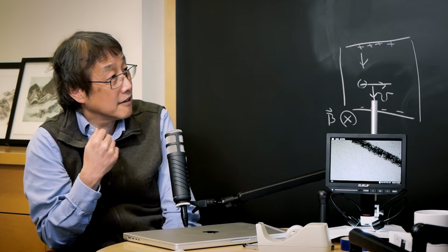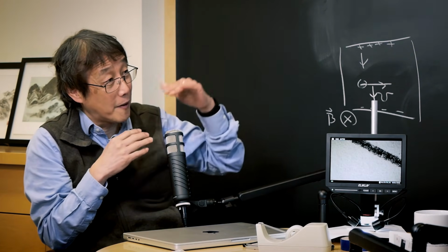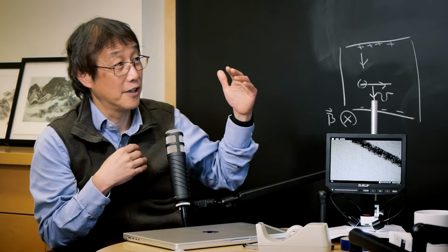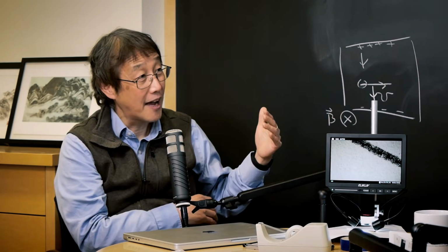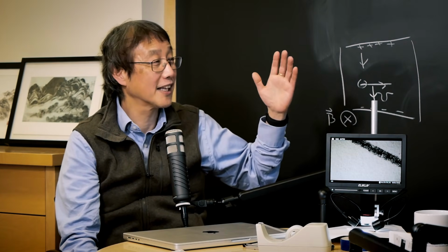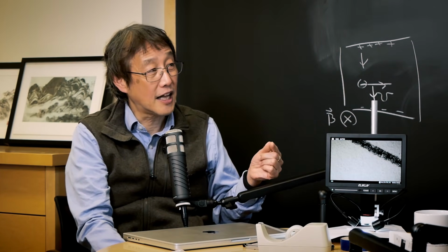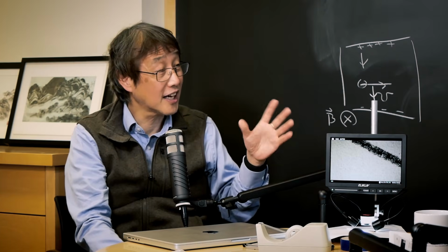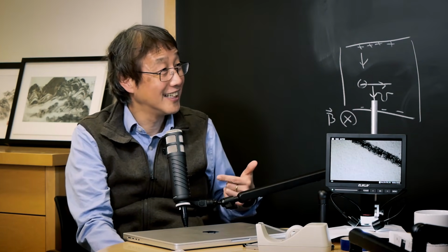Once the quantum Hall effect is there, the immediate thing you notice is that graphene quantum Hall is different from gallium arsenide because of the linear dispersion relation. Therefore, the Landau level separation is not uniform, unlike in gallium arsenide. Especially the first Landau level is really well separated out. That energy gap, if you convert it to temperature, is 1,000 Kelvin. It depends, but at 20 or 30 Tesla of magnetic field, it is 1,000 Kelvin of separation, so it is really well separated. Of course, gap size is not the only important part; you also need low disorder. So you eventually need to go to a high enough magnetic field to see this at higher temperature, right?